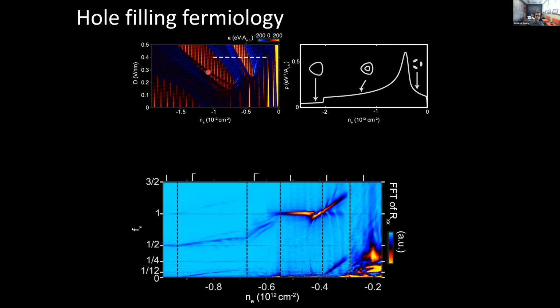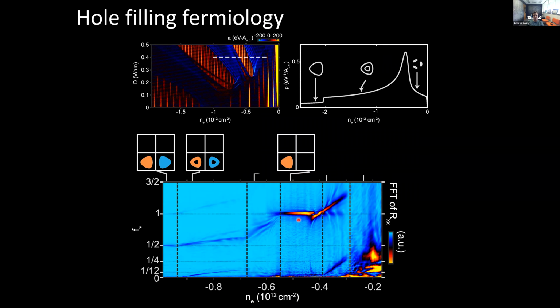Okay, and then this pattern tends to repeat, so you can go through this in a variety of other places where, again, you see now a half metal where you just have 2 out of 4 of the natural Fermi surfaces, a half metal with annular Fermi surfaces, a quarter metal where you simply have spin and valley polarization, a quarter metal with annular Fermi surfaces, and then additional partially isospin polarized phases, and so on.